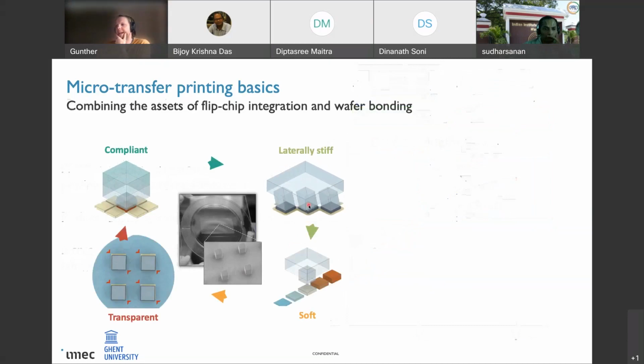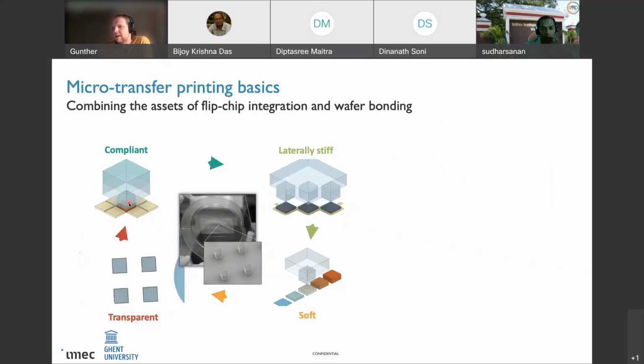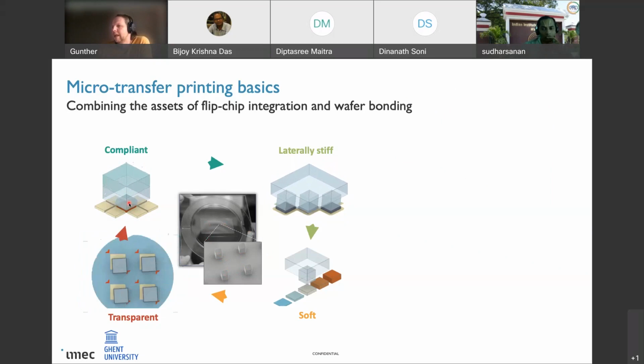So this is then how it looks. This is a picture of such a stamp on a glass plate. You see that you can make these structured posts on it to pick up a subset of devices. This PDMS is compliant. That means you can overdrive the stamp onto your source and target wafer to get an intimate contact between the two.